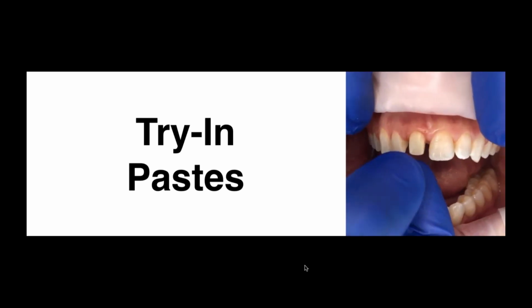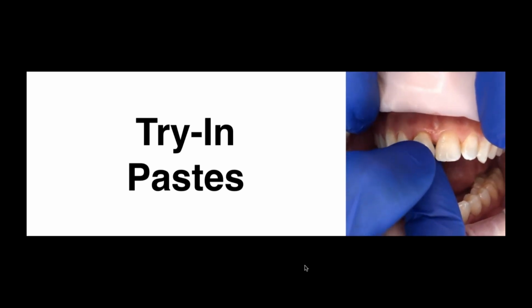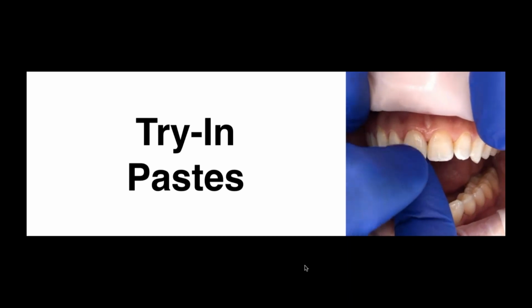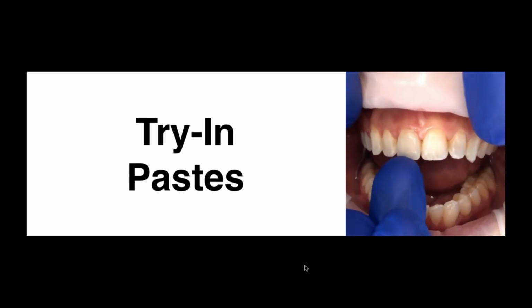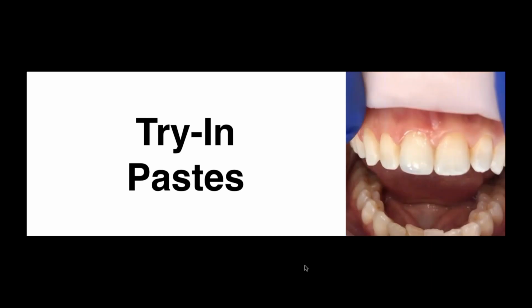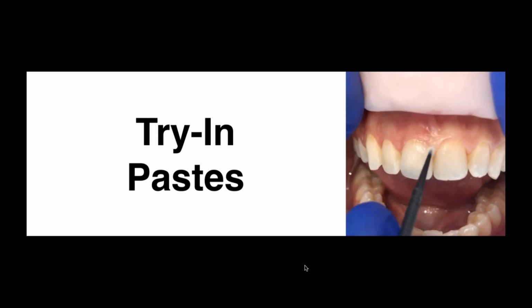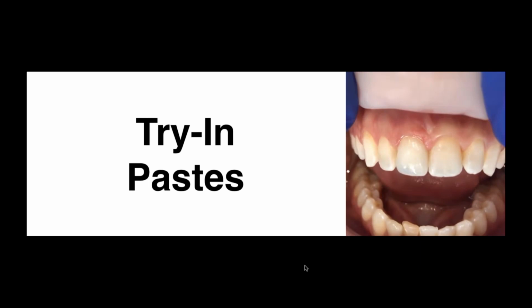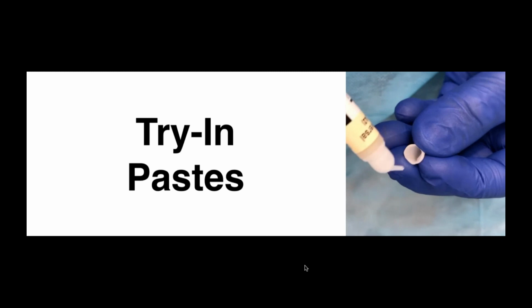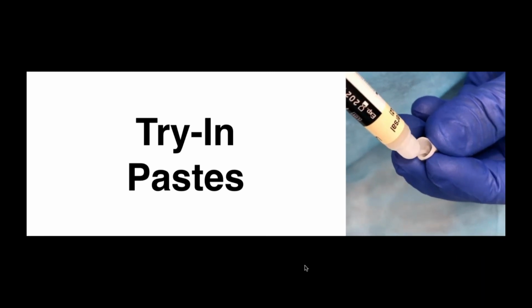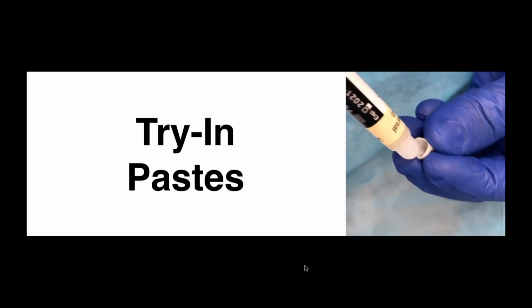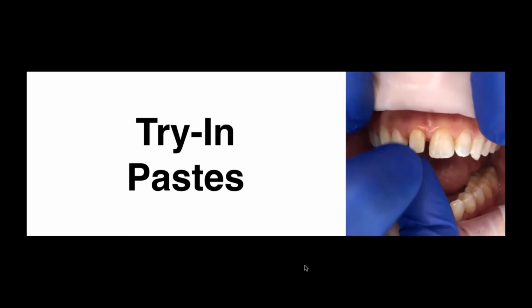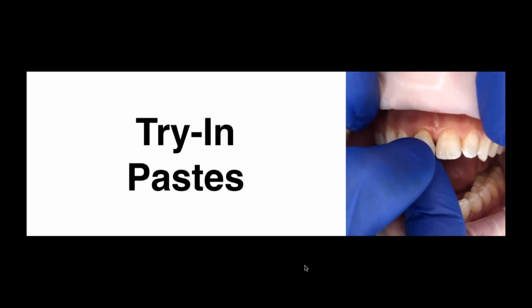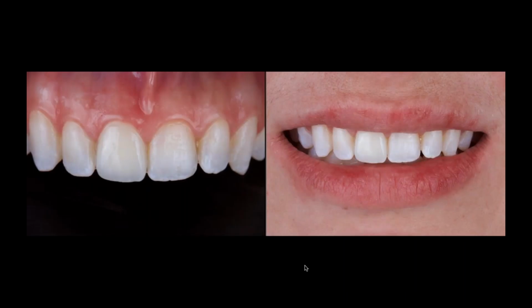Here for single centrals, I always start with the translucent try-in paste, and then if I see that maybe I would like to have a little bit more chroma, then I go with the A2 universal try-in paste. This is the Panavia V5 try-in pastes, and once I confirm this, then I would go and remove the restoration, clean it in the ultrasonic with alcohol to make sure I remove all the residues of the try-in paste, and then go for the adhesive cementation protocol on zirconia restorations that I will explain in a minute. And this is the final outcome.